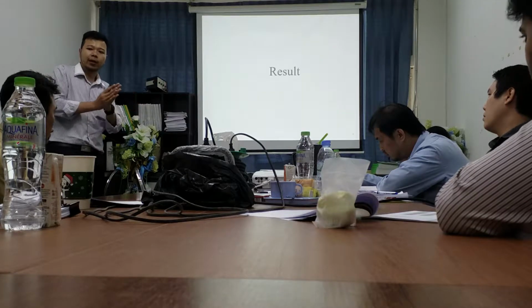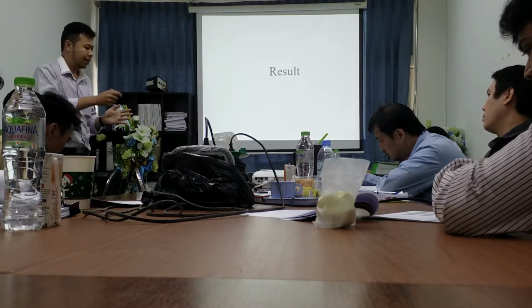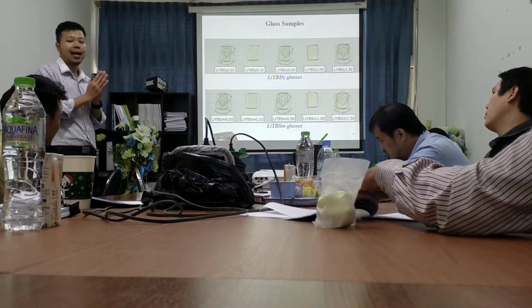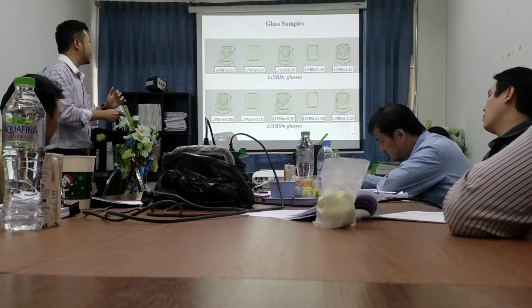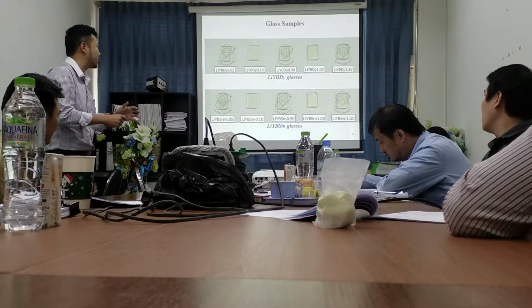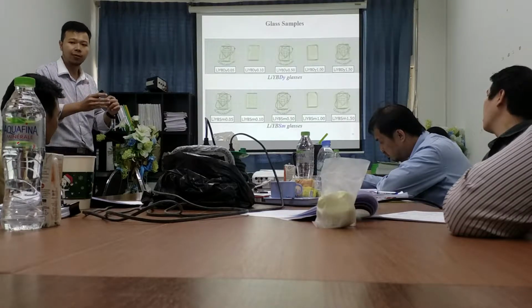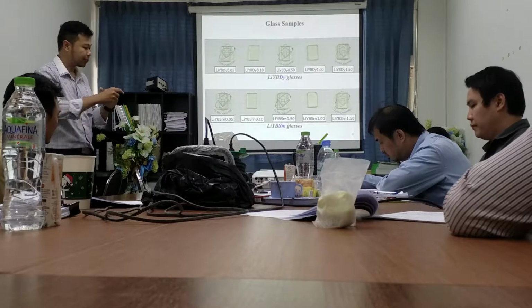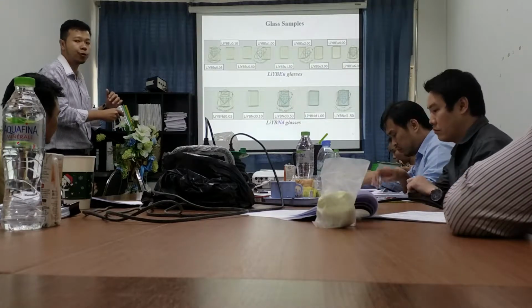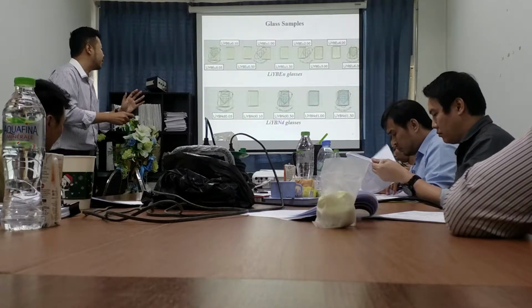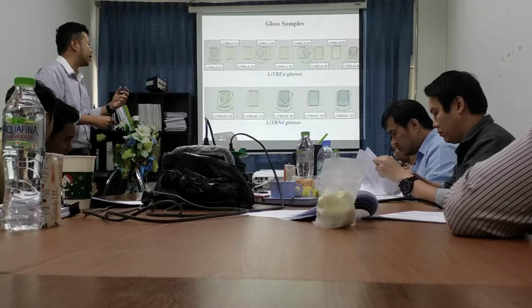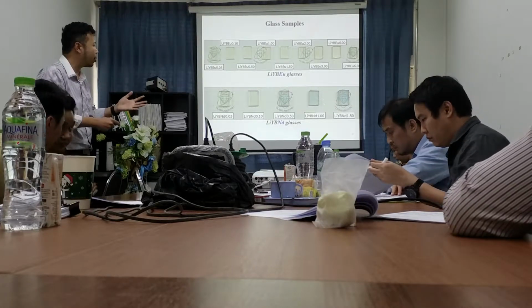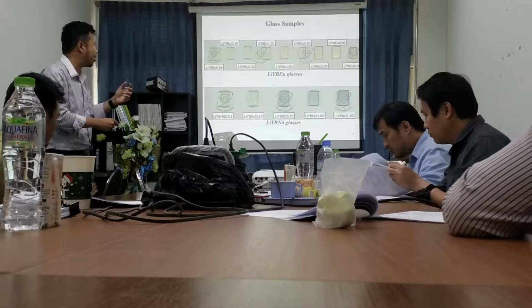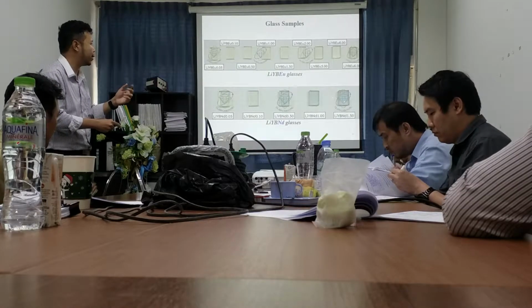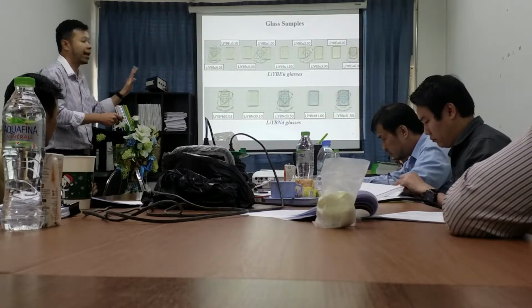Next, I move on to the result section. Start with the glass samples. This is the Dy-doped glass and Samarium-doped glass, which show the same outlook, light yellow and good transparency. Also the Europium-doped glass shows a light color and good transparency. But for the Nd glass, when we dope more and more neodymium oxide into the glass, the color of the glass changes from yellow to blue. Just Nd only.